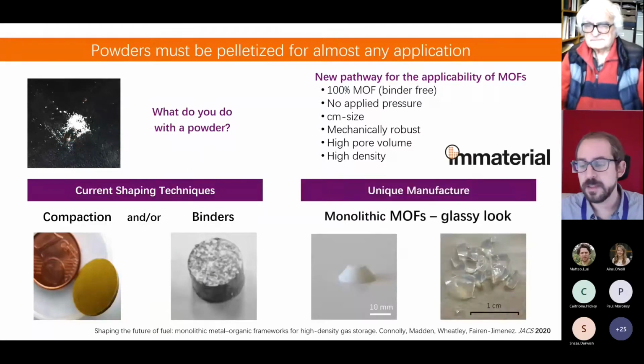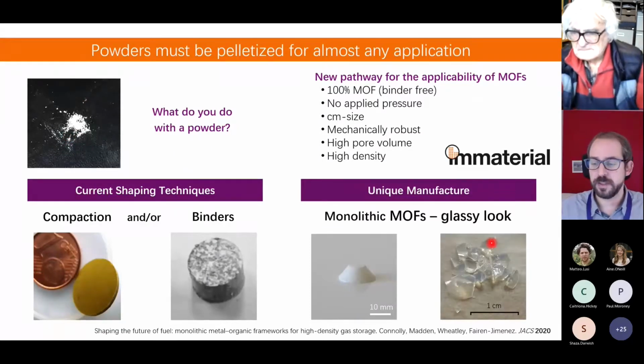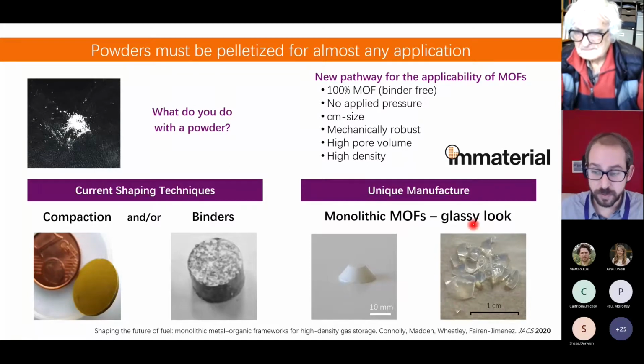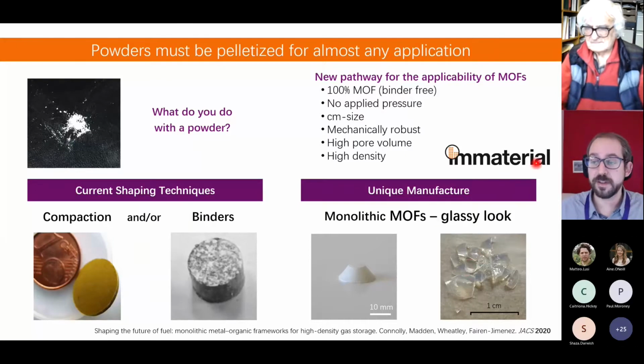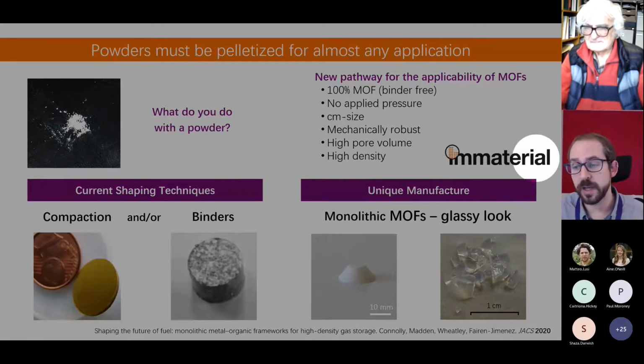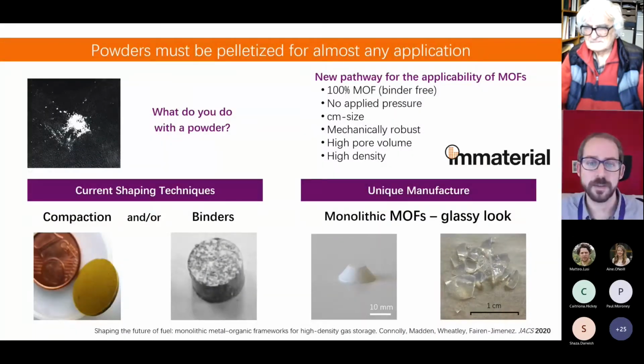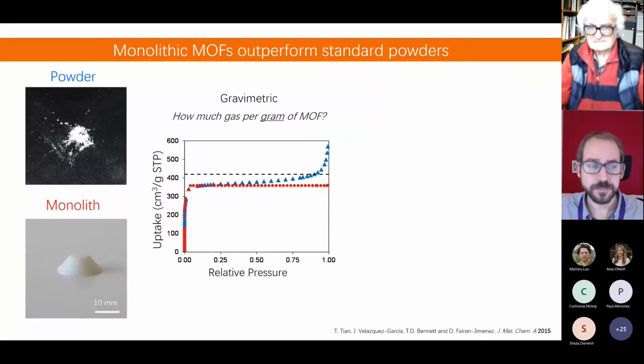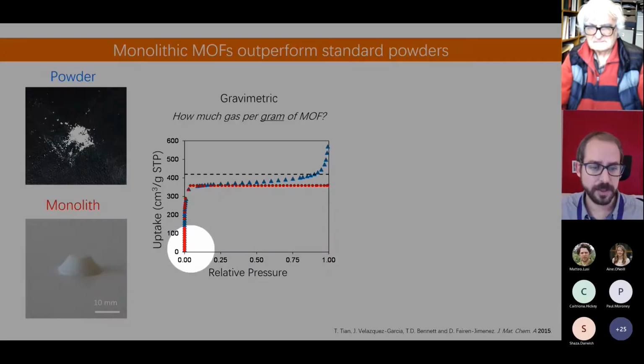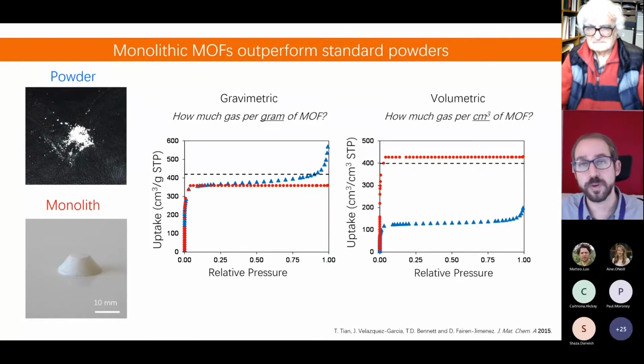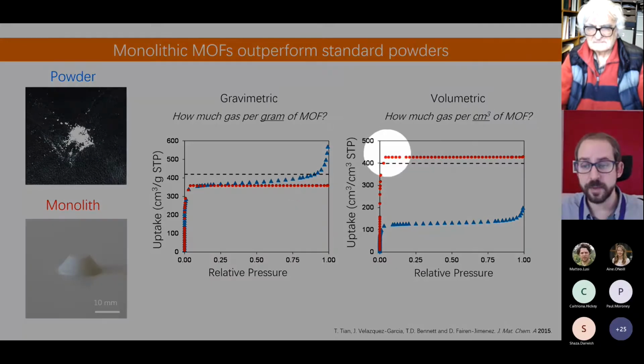And these are the results that we have with these materials. We have this beautiful glassy looking material, but they are fully crystalline, fully porous materials. And as was said in the introduction, this is something that we are exploiting with our spin-out company. This is the comparison of the powder and the monolithic material. These are the nitrogen isotherms, no difference from the gravimetric point of view, but if we go to the volumetric, the density of the monolith is 3 or 4 times higher than the density of the powder, and therefore the uptake is much higher.